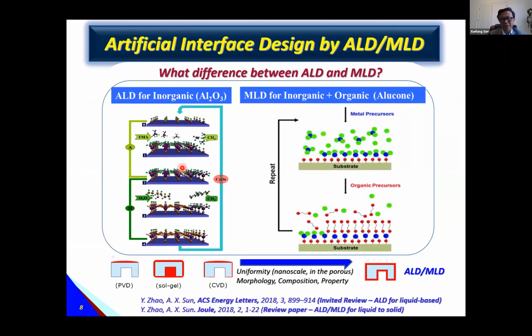Here we see how to synthesize good ionic conductive coatings using ALD. For example, ALD is generally for inorganic materials, which could contain lithium. When we move to organic materials, we call this molecular layer deposition, using the same machine. We can also combine inorganic and organic to tune the mechanical and other properties. That's why our group dedicates a lot of effort to this technique.